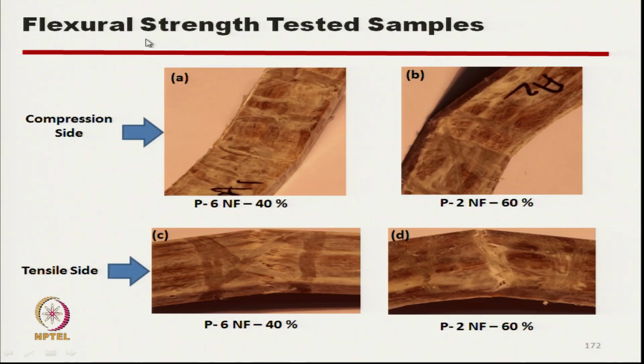Now, if we see these pictures, this shows what is happening after flexural strength testing. Here this is the compression side and this one is the tensile side. On the compression side, with number of passages of, say, 6, as the matrix and reinforcing fibers are evenly distributed, there is no delamination or less delamination, but at a lower level of mixing we can see they are getting easily delaminated.